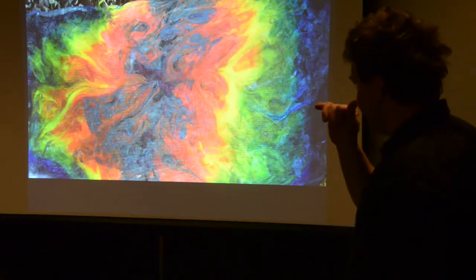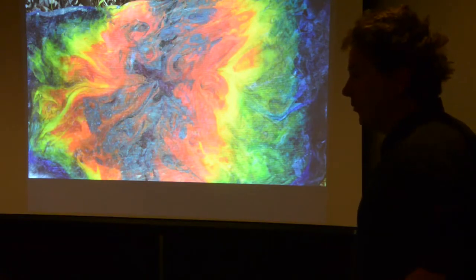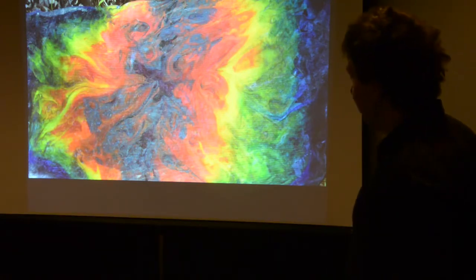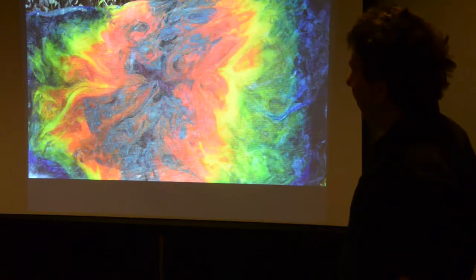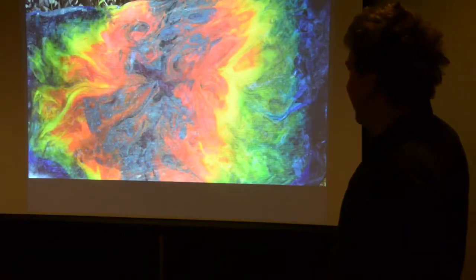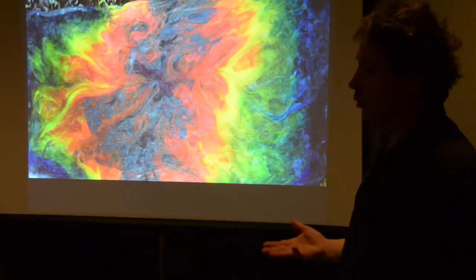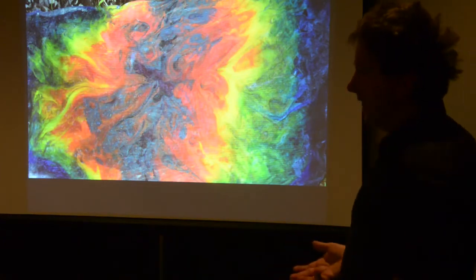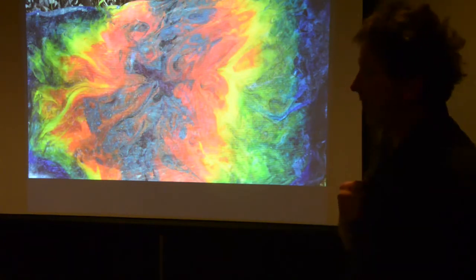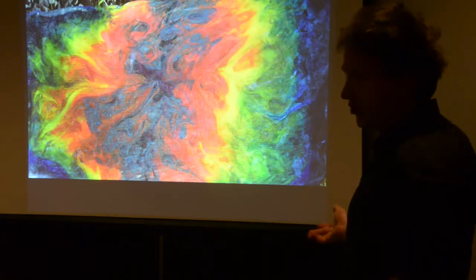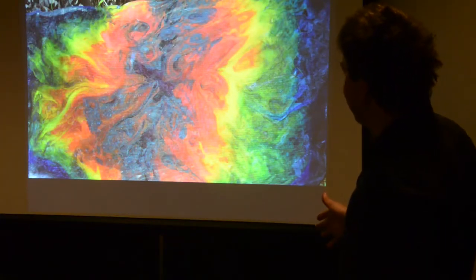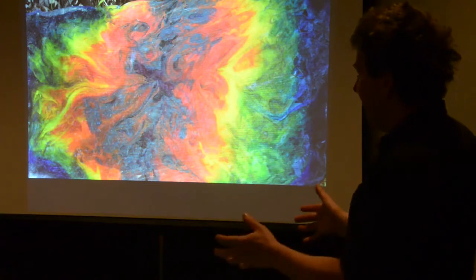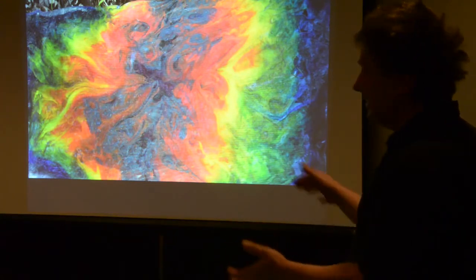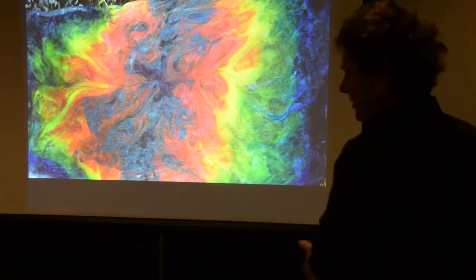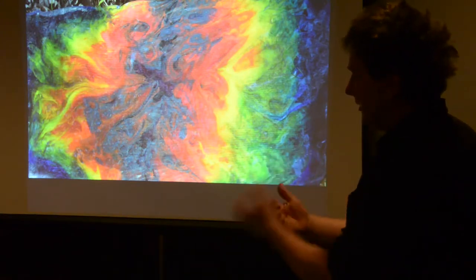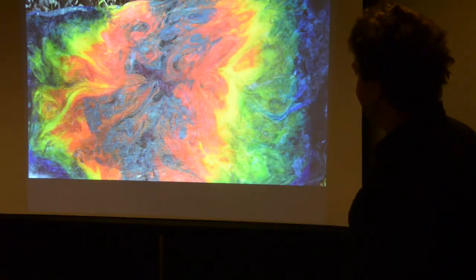The yellows are harder to do. It's cadmium and selenium for the reds and yellows. I don't do that myself because when you add cadmium and selenium to your glass batch, it will evolve, it'll boil off up to 90% into the air. So you'll be sucking in more of the cadmium than actually putting color into the glass, and it just sucks. Back in the day, they used to mix the glass batch with the cadmium and put it in sealed clay jars and put that in the furnace and cook it for a long time until it gets in there, and that's a good way to seal it together.